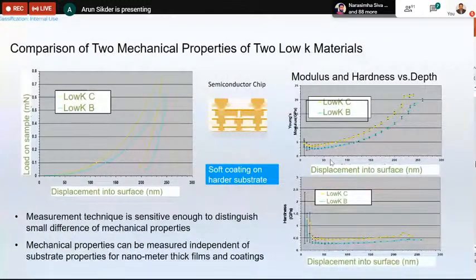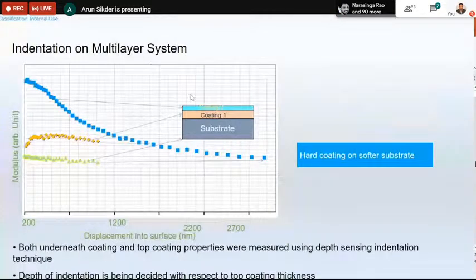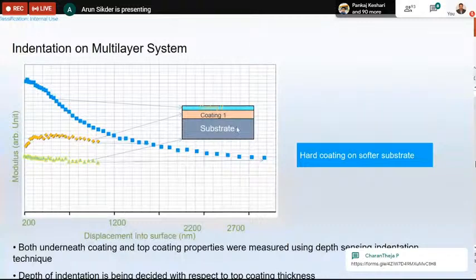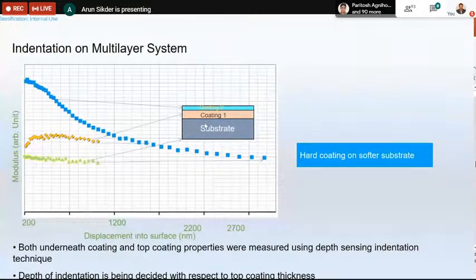So that is the kind of importance of the measurement techniques you need to know. This is another example. This is a substrate which has different layers, coating one and coating two. Now, if I test the substrate and the coating separately, this is the modulus with respect to the depth. My substrate is not changing; it is a straight line. For the coating, slowly it goes down because the coating is on the substrate. The coating is higher hardness than the substrate. So if I go to more and more depth, somewhere it will come to the substrate value. Now, in this entire coating range, I'm doing indentations, and if I go slowly, you can see it is reaching towards the substrate values.